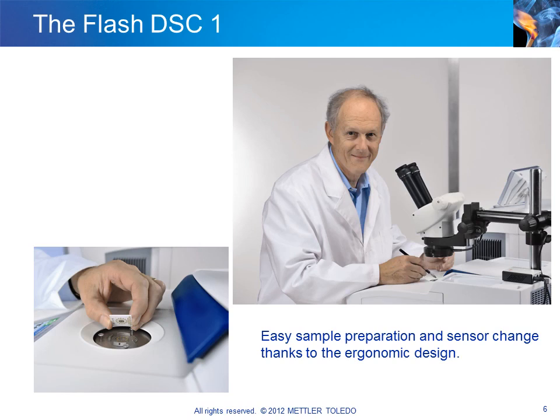In order to achieve the ultra-high heating rates, the mass of a sample is typically a few micrograms down to nanograms. The preparation and insertion of such a very small sample is performed sitting comfortably in front of the instrument. To ensure optimum thermal contact, the sample is positioned directly on the sensor. This is done using a microscope. This ensures simple and reliable sample handling.